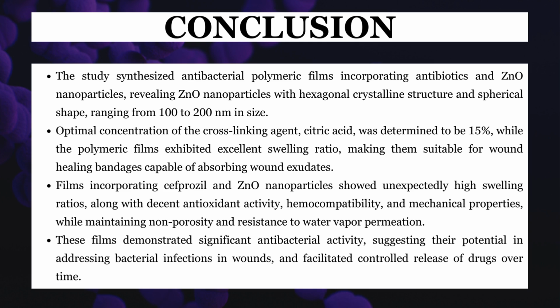Films incorporating cefprozil and ZnO nanoparticles showed unexpectedly high swelling ratios, along with decent antioxidant activity, hemocompatibility, and mechanical properties, while maintaining non-porosity and resistance to water vapor permeation. These films demonstrated significant antibacterial activity, suggesting their potential in addressing bacterial infections in wounds, and facilitated controlled release of drugs over time. Future perspectives.